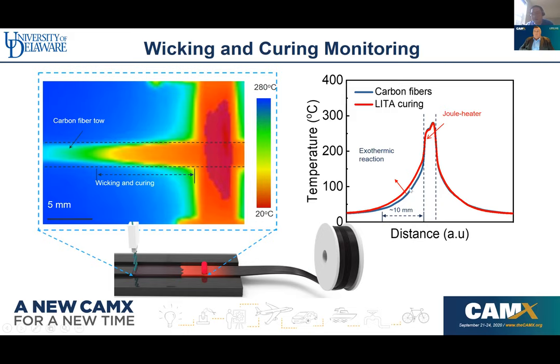So a little bit of increase for the red one, which is the later curing. The increase of temperature comes from the exothermic reaction of the epoxy resins. So this confirms that the gradient temperature distribution can actually trigger the reaction and curing of our epoxy.